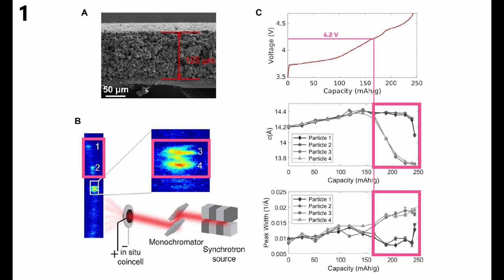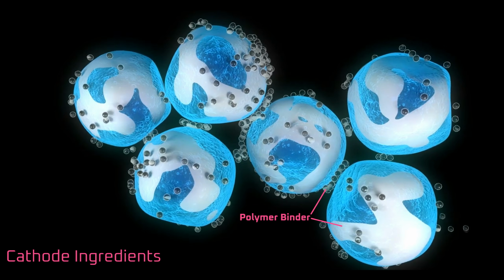So what's going on here? As I said a moment ago, in a wet slurry-based coating process, the binder is dissolved into solution and coats all of the particles as the solvent dries, holding the cathode film together. What I didn't mention is that the binder is an electronic insulator, which can interrupt the flow of electrons through the cathode film. So different regions, and therefore particles within the cathode film, have greater or lesser access to the electrons that drive chemical reactions.